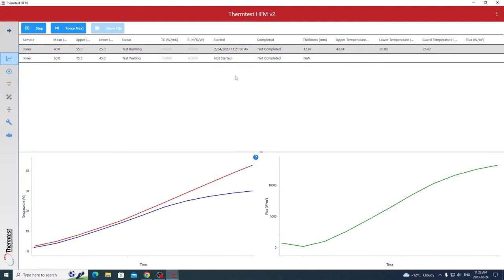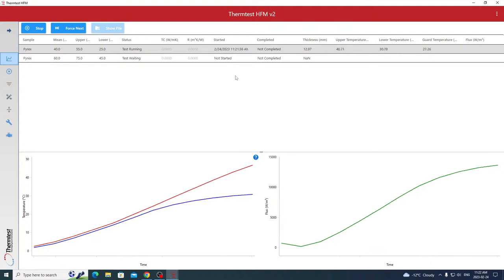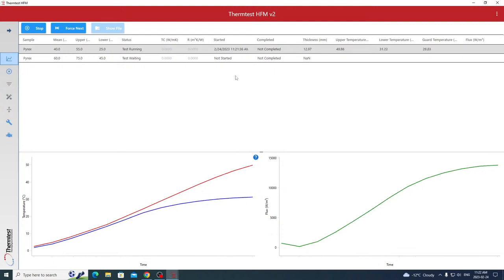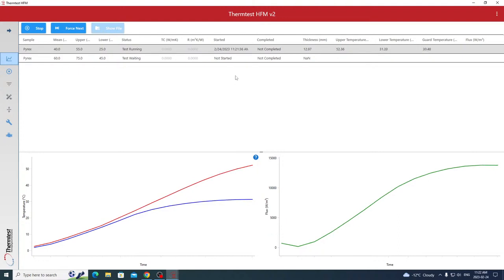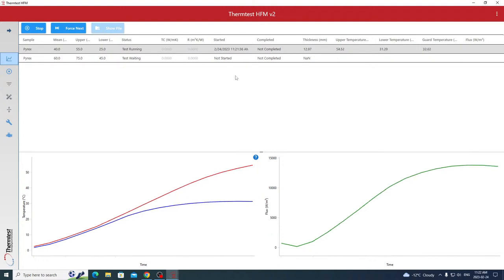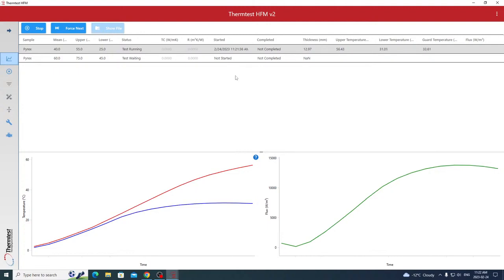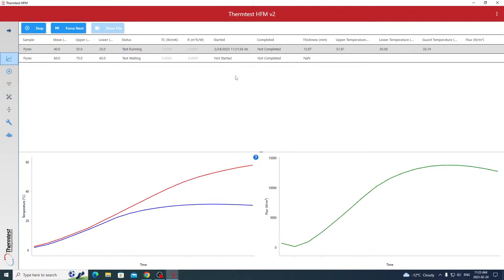The average time of measurements is roughly around half an hour. And then to go to another temperature is another half an hour. Now, one of the things that we talk about with transient methods is that it's fast. One thing to consider is that most transient measurements we are measuring 5 or 6 times just to get a good average value. In each of those measurements, there's a delay of 5 to 10 minutes between each one to allow the heat you introduce from that transient measurement to dissipate. Otherwise, you're going to get internal drift.